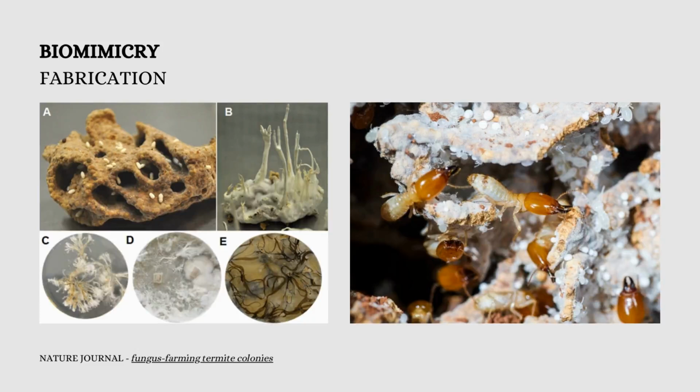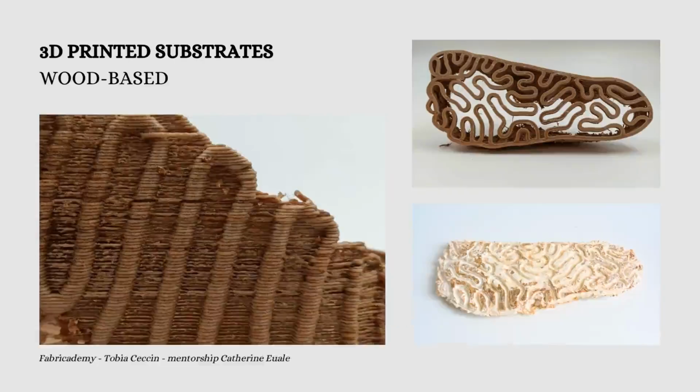However, there are other gellants and things that you might put in there that might not extrude as easily, and you might have to try a few different parameters for speed, for instance, and for pressure, that will allow you to just see what works and what doesn't. And density also of your material. Maybe you have to add a little bit more water or add less clay if you find that it's really dense and it's not coming out of the nozzle, it's not extruding.